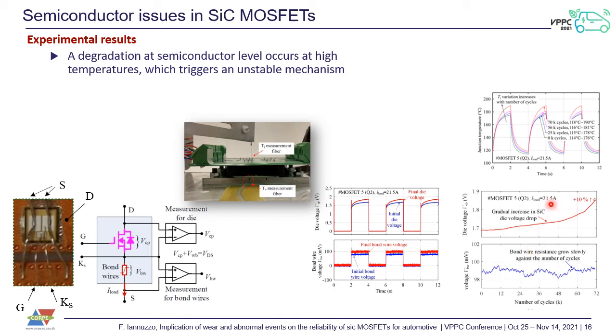Junction temperature was also drifting up with time, which means that this is not just a measurement error. As a matter of fact, higher voltage means higher power at the same current, which is forced from the outside, and this ends up in a higher temperature swing, as you can see from this picture, where the initial temperature swing is the bottom curve, the blue one, and then the green and the two red ones on the top.